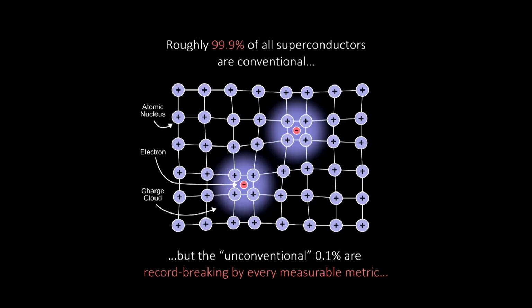We wouldn't really think twice about this. But the thesis of today's talk, and the dedication of thousands of physicists' careers to this effort, is that this 0.1%, these so-called unconventional superconductors, are really important. Namely, they're important because they're record-breaking by every metric. They survive to the highest temperatures, the highest magnetic fields, and the lowest densities that we measure in these systems. So they're really robust superconducting states.